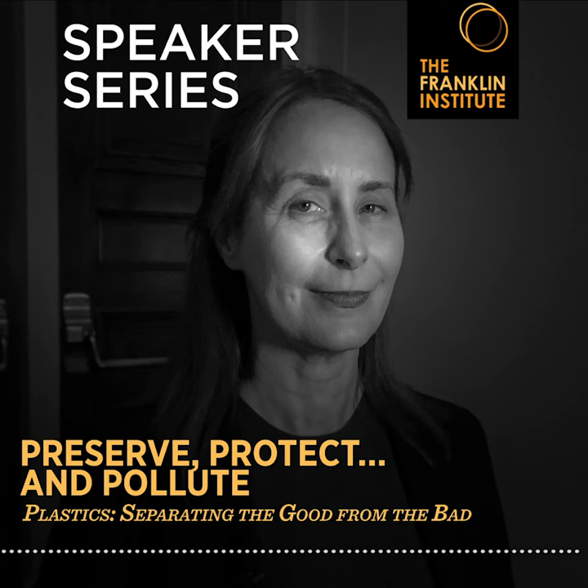We're made of plastic — we're just made of natural plastics. We're made of proteins. The world is also full of cellulose, the world's most abundant polymer. And it's modifications of these — specifically of elephant ivory in the beginning, trying to replace elephant ivory and tortoiseshell — that gave us our first synthetic plastics. The first one is called celluloid, a brand name for something called cellulose nitrate. Cellulose nitrate had a bigger public safety problem than anything we have now: it caught on fire on its own. It would immolate theaters full of people and factories full of workers. That was a problem, but we overcame it. It took about 50 years to do that.